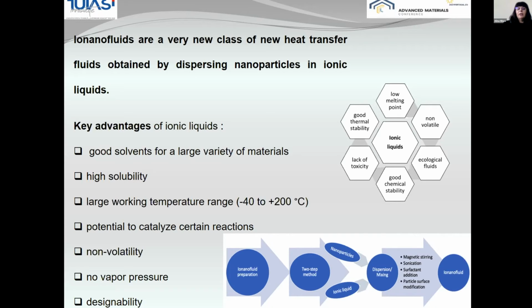The preparation of ionanofluids is the same as for all nanofluids, and the most traditional method is the two-step method, when ionic liquid and nanoparticles are mixed together, and the next step being the dispersion. And the dispersion can be stabilized by magnetic stirring, sonication, particle surface modification, or surfactant addition. The surfactant addition can assure a good stability. Nevertheless, if we are adding surfactants, the thermophysical properties control is somehow lost. So we have to be very careful if we need the addition of a surfactant.